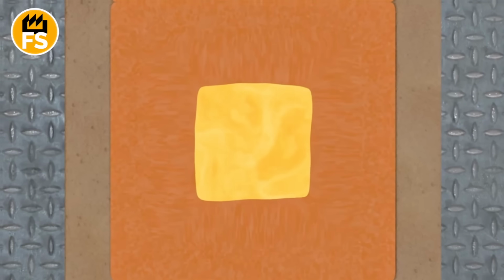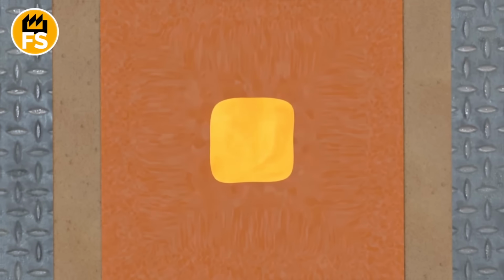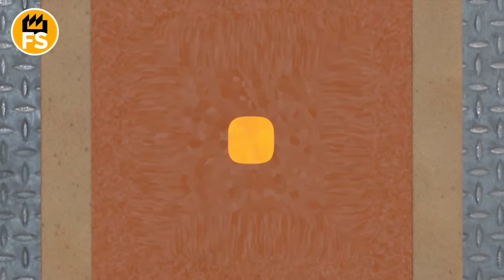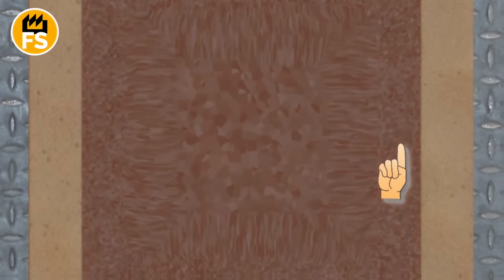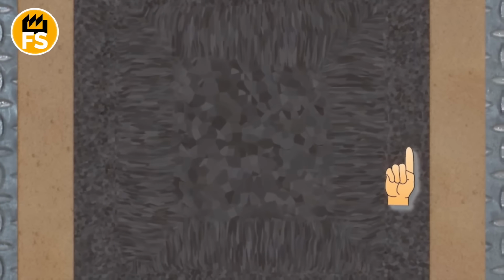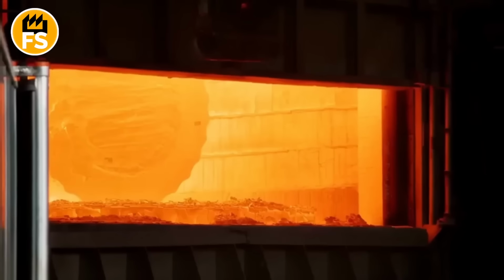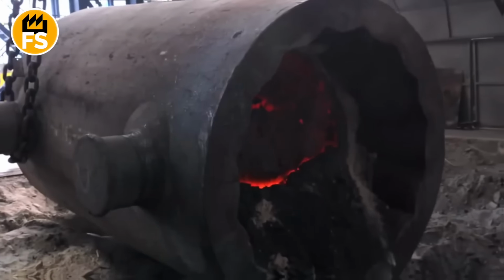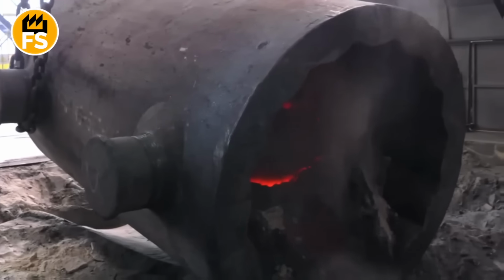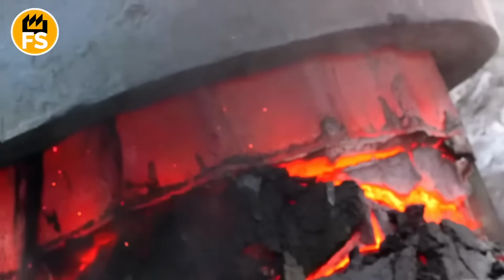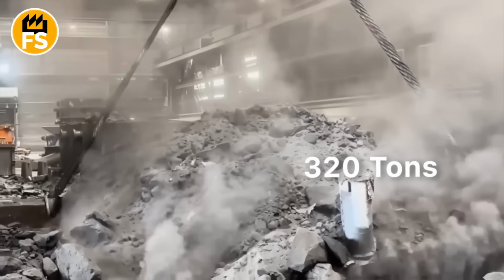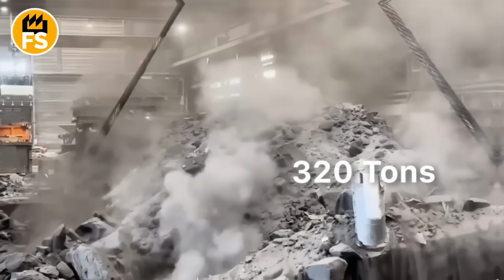This slow crystallization allows the metal to avoid unwanted phase transformations and guarantees a high-quality macrostructure, which is the key to the strength of the future component. Only after this lengthy solidification period is complete, the steel monolith, which after shrinkage and removal of the defective top portion weighs approximately 320 tons, is carefully extracted from the ground.